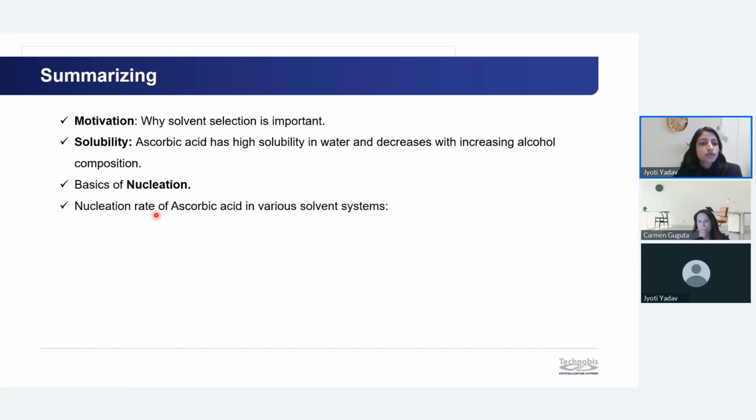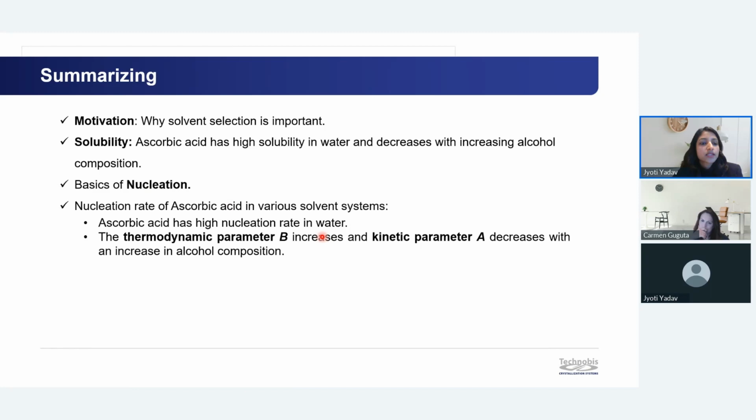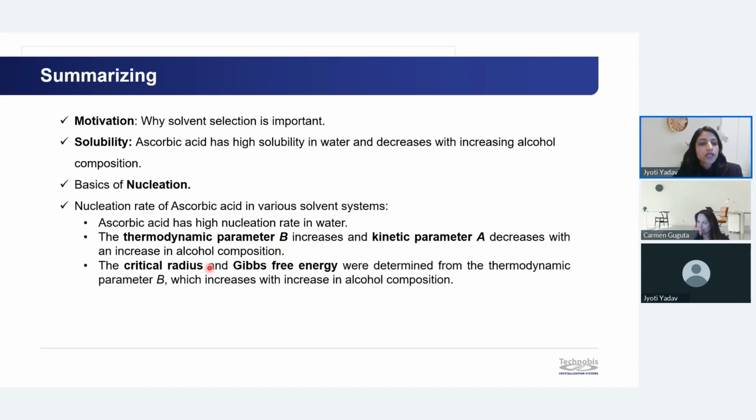And the effect of solvent composition on nucleation rate of ascorbic acid in various solvent systems, and saw that ascorbic acid has a high nucleation rate in water. Then the thermodynamic parameter B, which represents the activation energy required for nucleation, increases, and the kinetic parameter, which represents the number of active sites available for nucleation, decreases with an increase in alcohol composition. The critical radius and Gibbs free energy were determined from the thermodynamic parameter, and increase with increase in alcohol composition.